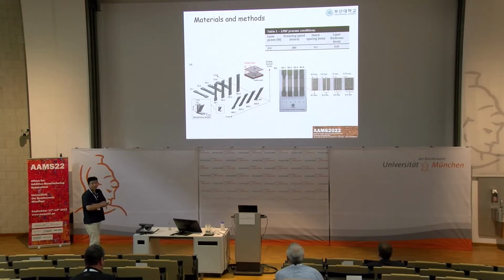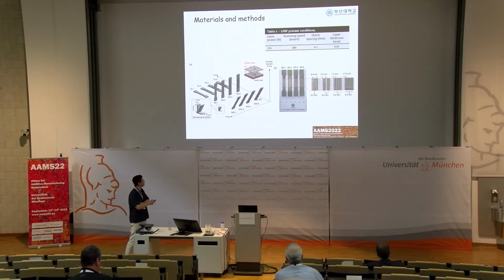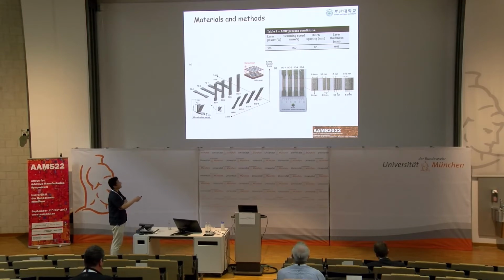For this, we developed a special experiment. Here is our specially designed tensile specimen shape. Here we have 4 different types of specimen geometries. It's basically a tensile specimen, and sample series 1 has the simple geometry like the normal tensile specimen, and sample series 2, 4, 8 has divided beams in the tensile gauge length. So we are basically increasing the surface area while keeping the overall cross-sectional area the same.